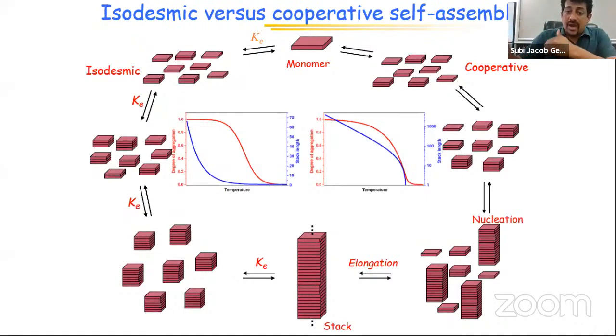Similarly, what is identified in supramolecular polymers is the nucleation growth mechanism, or a cooperative mechanism. There is an energetically unfavorable process of nucleus formation. And once nucleation happens, elongation, which is analogous to propagation in classical polymer chemistry, takes place, and you get a stack of very high molecular weight. So a lot of attempts have been made to understand the important parameters which determine this mechanism.